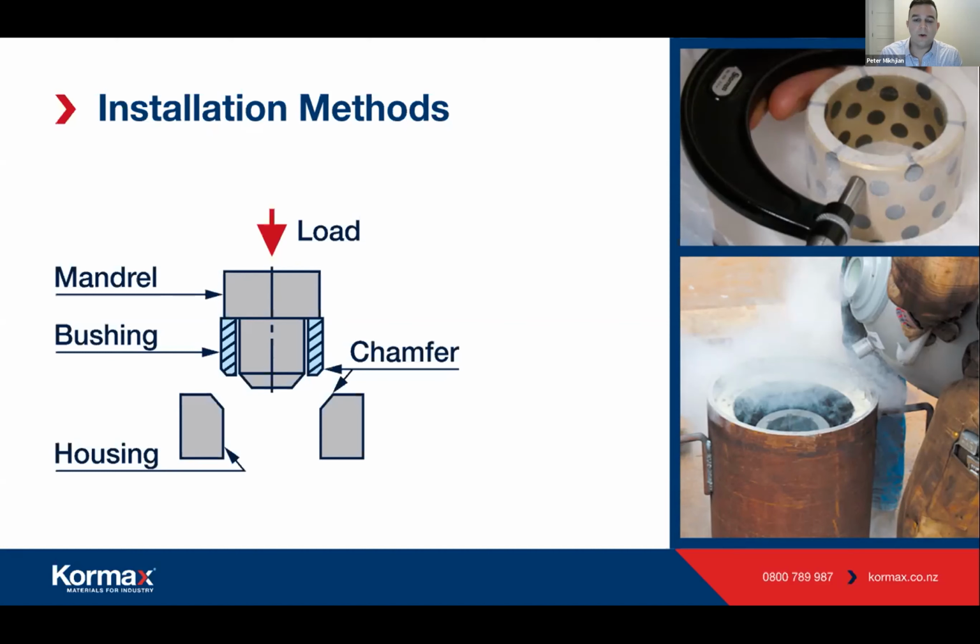After roughly an hour in dry ice, the bearing should have sufficiently shrunk in size to make it easier for installation. We just need to position it properly in the housing and allow it to sit untouched until the bearing reaches ambient temperature. We use the same method for liquid nitrogen. The only difference there being we'd recommend a shorter amount of cooling time, about a half hour versus an hour in dry ice. Half hour in liquid nitrogen is fine.